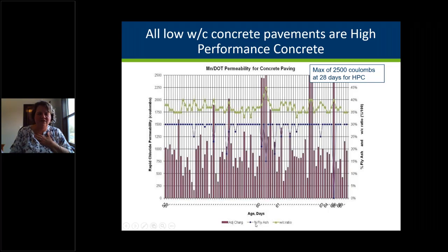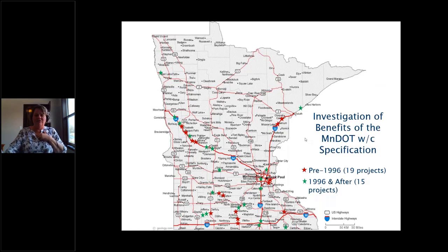What this graph also shows is that this blue dotted line is the percent fly ash in the mix. And when you decrease the percent fly ash, you saw the permeability increased. So we really found that use of SCMs was a great benefit. So how did we know this really was working though?